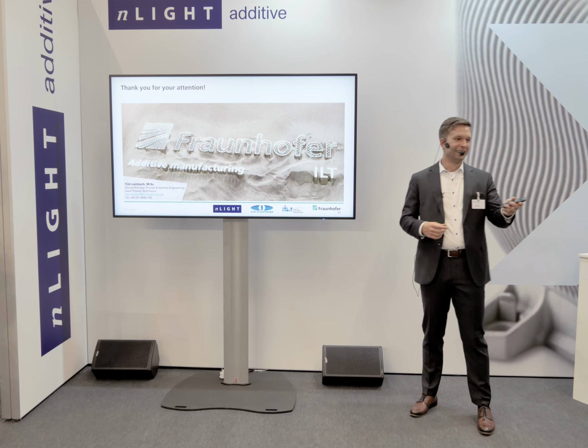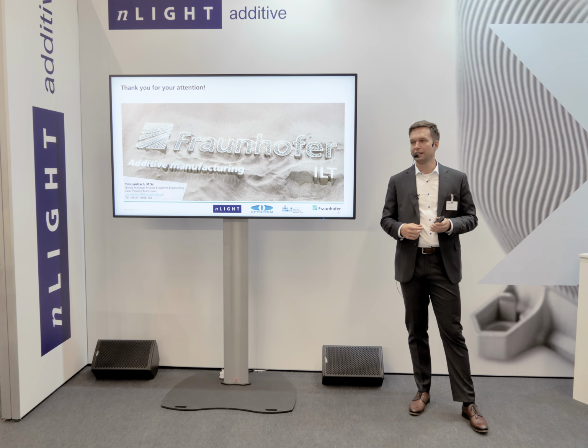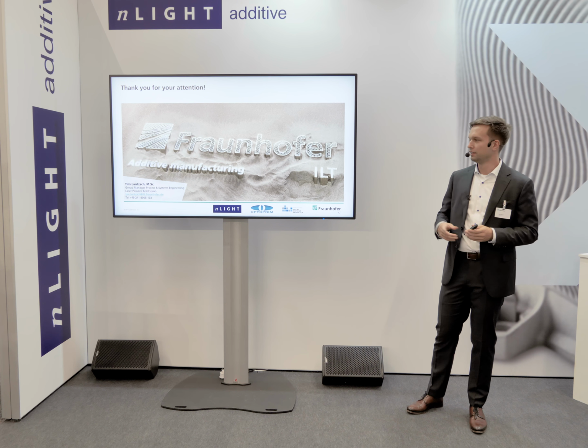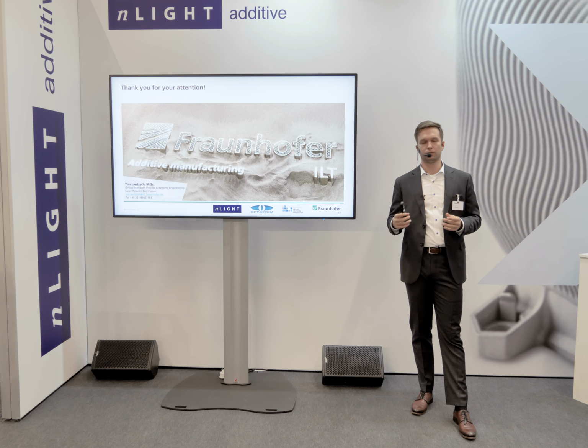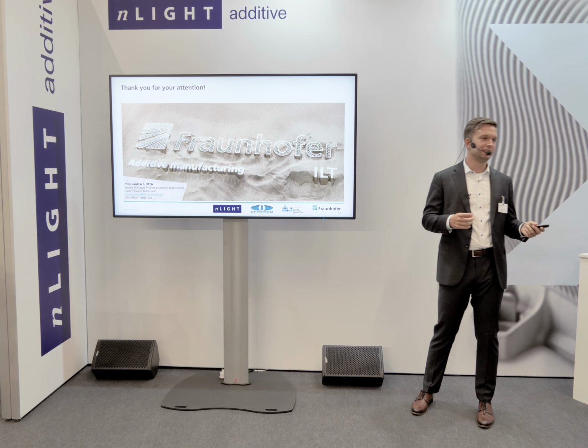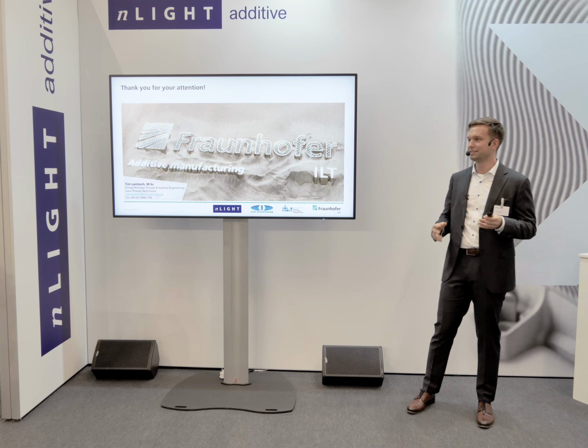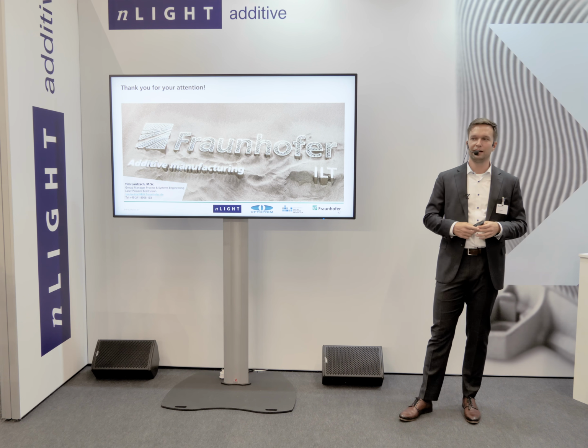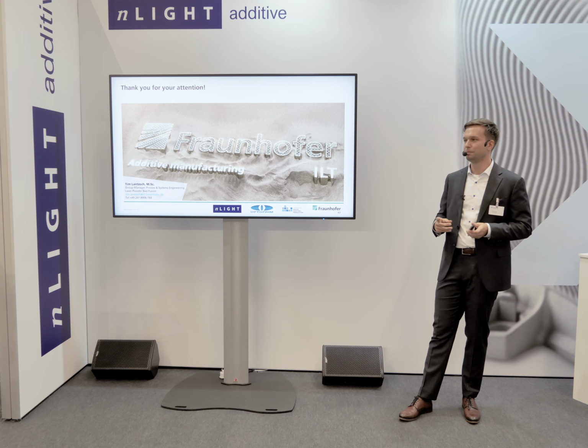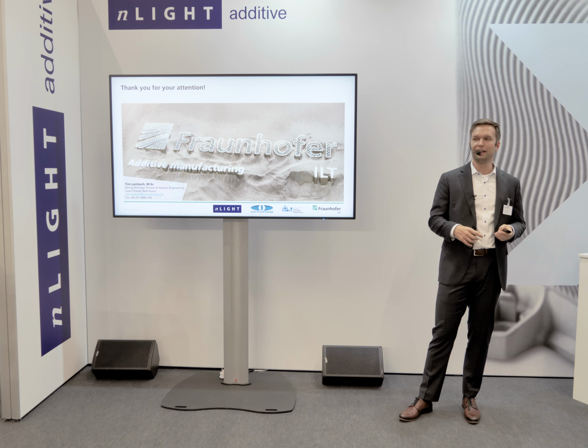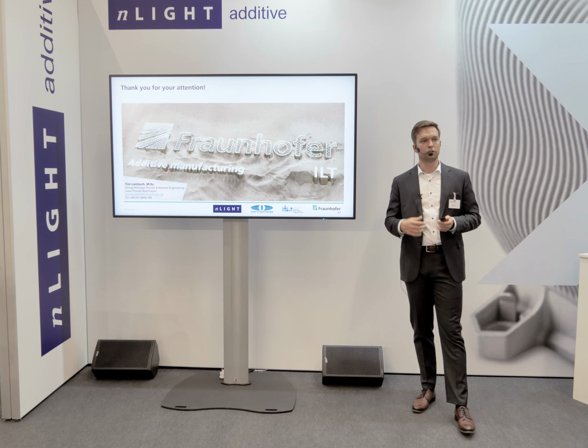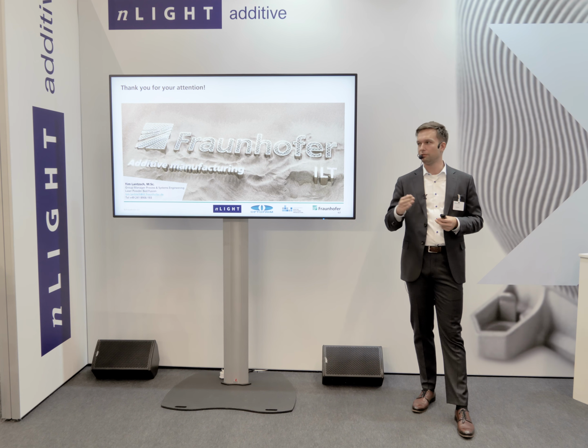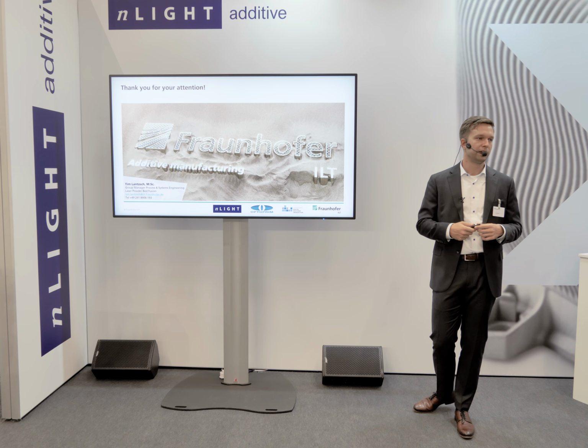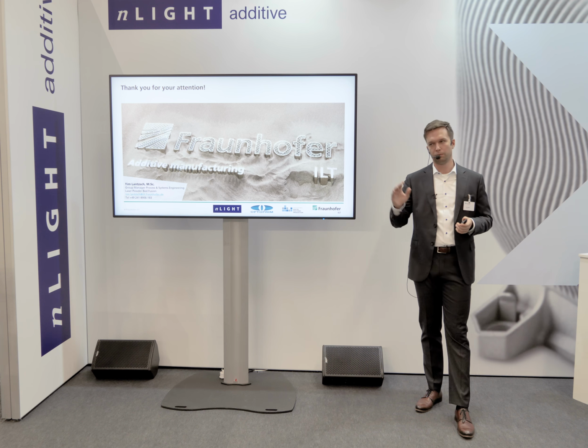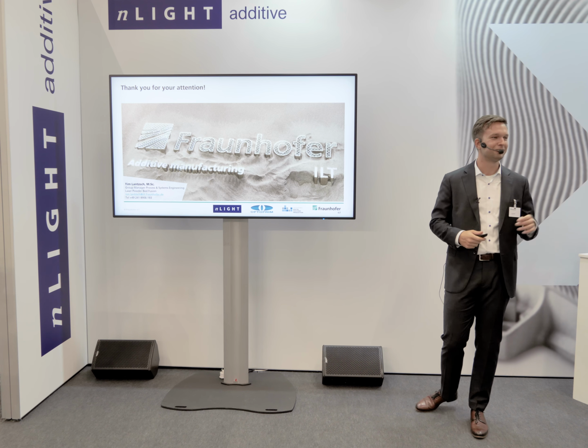Yeah. So the colleague here was asking if we also tried other settings and if we have also considered other settings, and that's true. We have stuck to the 3 settings here, which was our starting point. In the beginning we figured it was a good idea to have the almost 100% on both sides and the 50-50 in terms of power. We realized that because the ring is bigger, the 50-50 doesn't really make sense, because it's basically the high intensity peak in the middle that defines the process. So what could be really interesting would be to go more into the direction of having a 50-50 ratio in terms of intensity compared to the power ratio, and that would be probably more towards index 4, 5, something in this range.